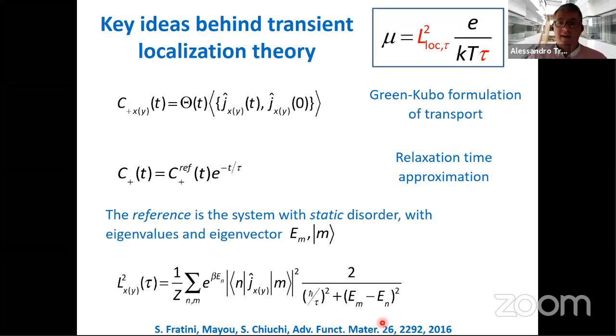So the idea is the following. We start with something which is correct, essentially using the Green-Kubo formula for transport, which says that the mobility can be computed by the current correlation function. So what they say is, okay, we know this correlation function at time 0 because it's the correlation function of a disordered material. And we know that it's going to decrease to 0 through some relaxation time.